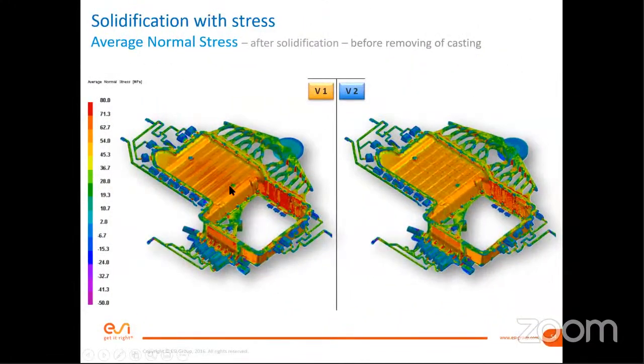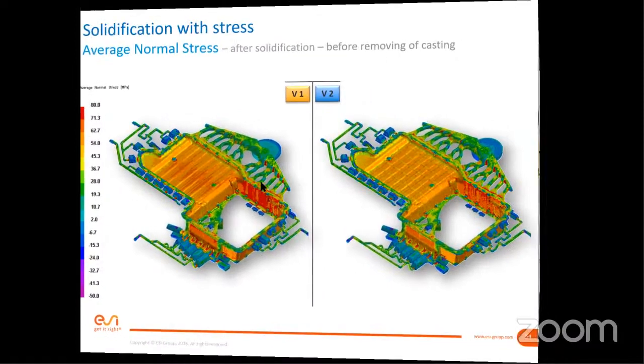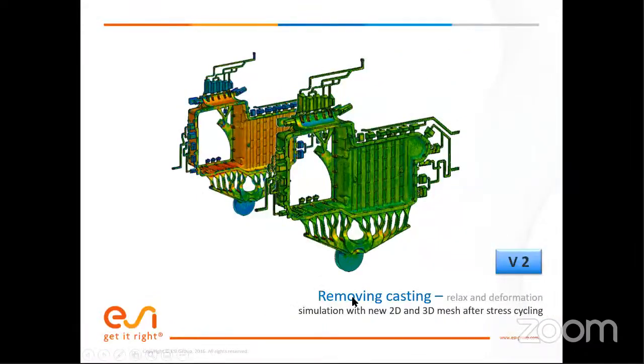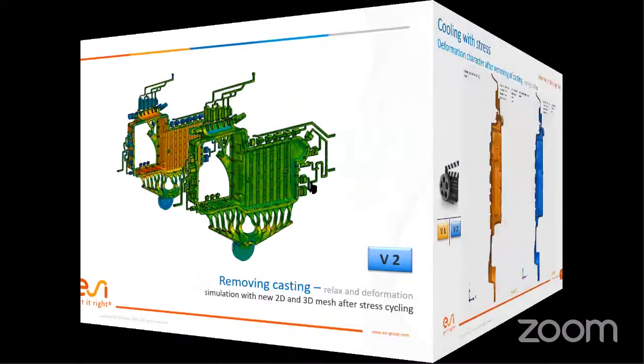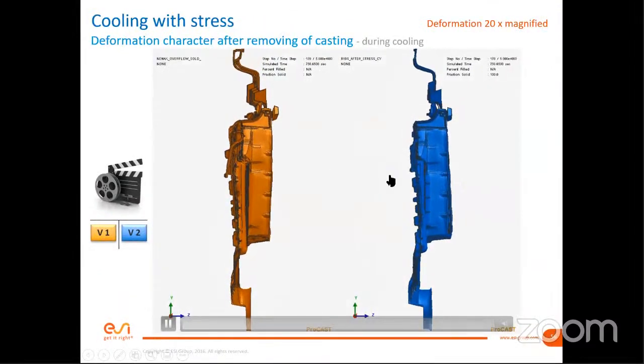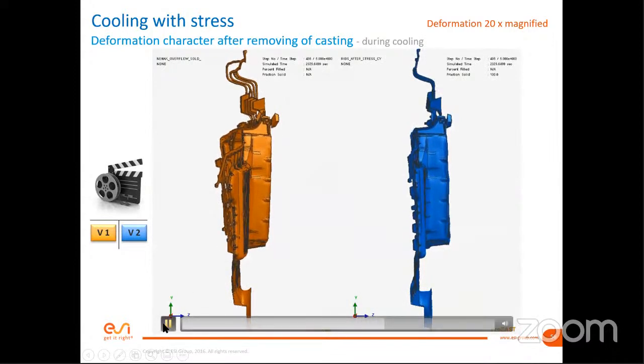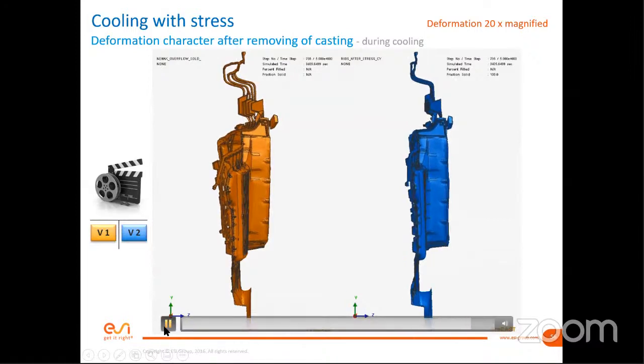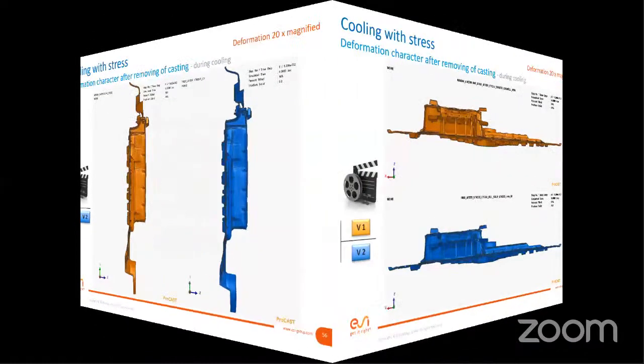So before the casting is ejected from the die, we have some distribution of the stress, and then the casting is removed from the die, which brings some spring back effect, which means that the stress which is generated in the die relaxed and became deformation. And we can see the deformation on the slides. And it's so visible how the first variant without the technological ribs is bending a lot in comparison with the second one, which is bending also, but with a very big difference here.